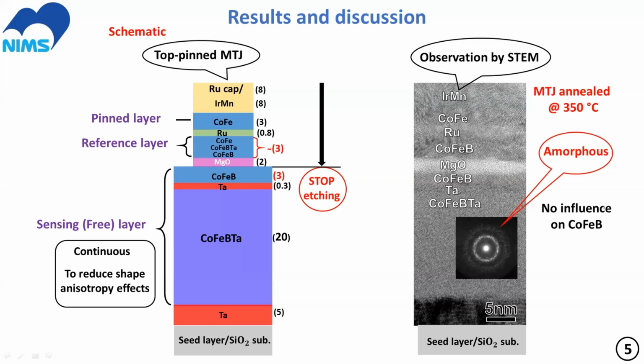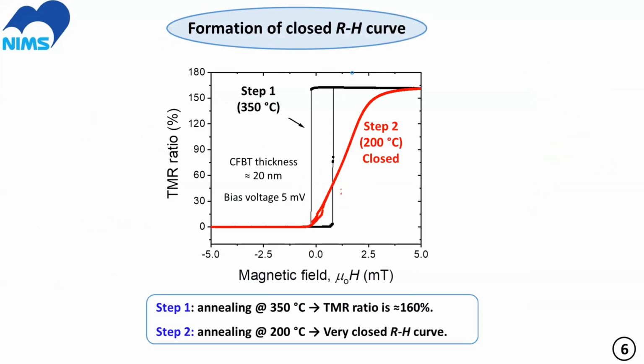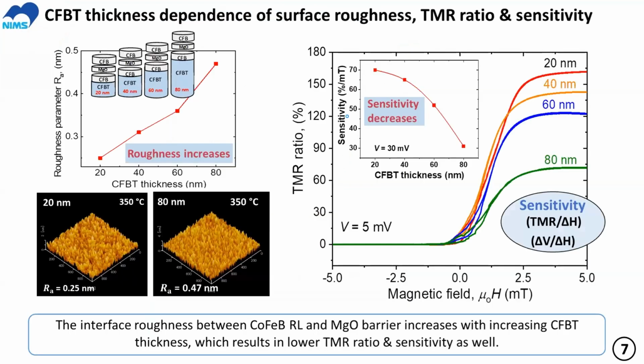It means there is no influence on the cobalt iron boron, and so we can get a high TMR ratio, and we can get a hysteresis-free curve. This I'm sharing with you here. The black curve is the hysteresis curve after the first annealing, and after the second annealing, you can see this is almost a hysteresis-free curve, very close and very linear, so it can work as a very good magnetic sensor. Actually, after that, we started to study the thickness dependence of the CFBT free layer.